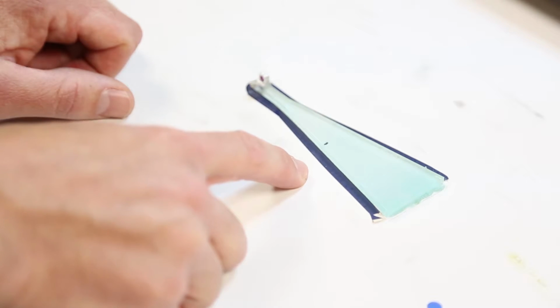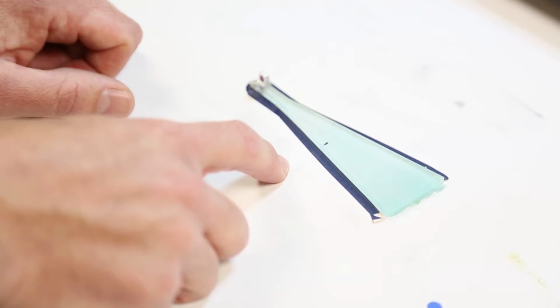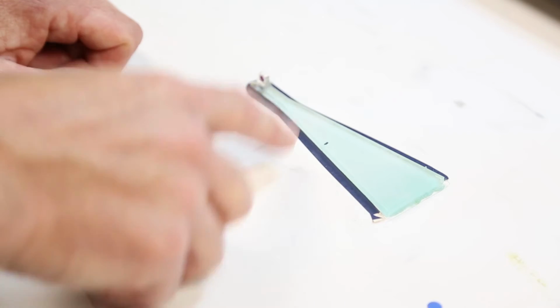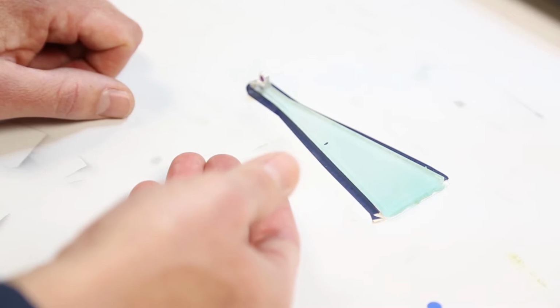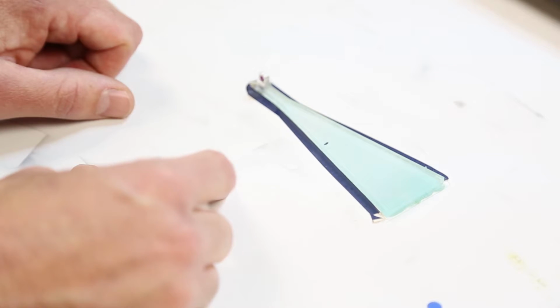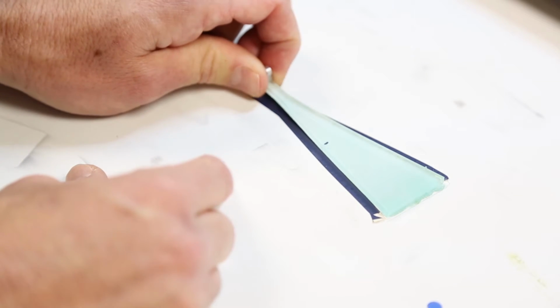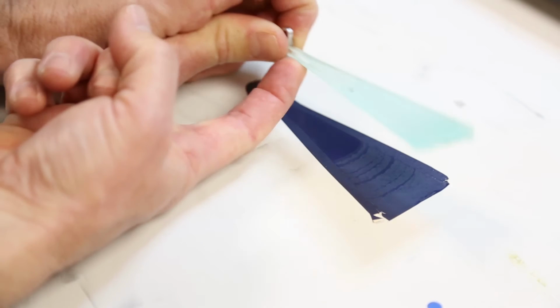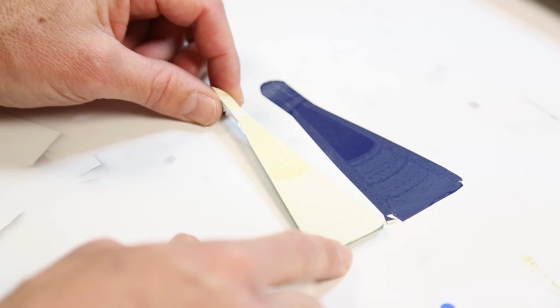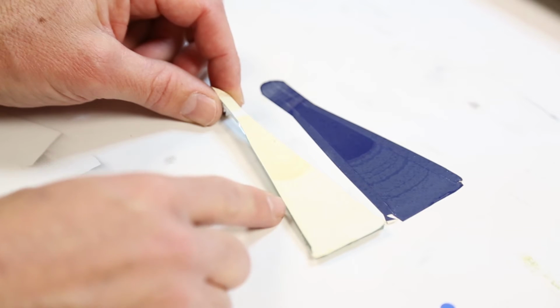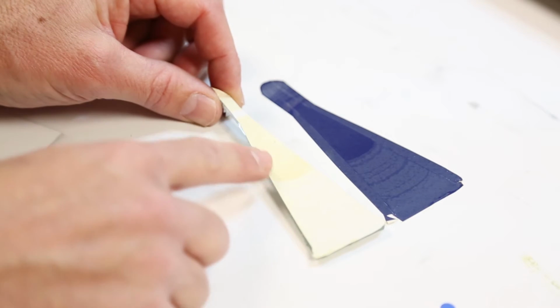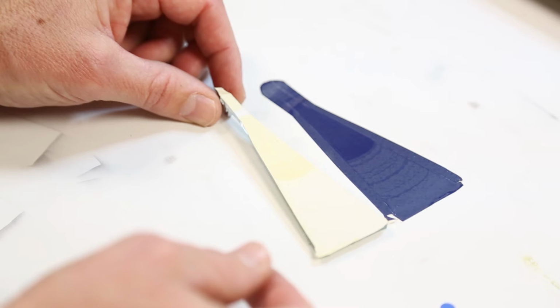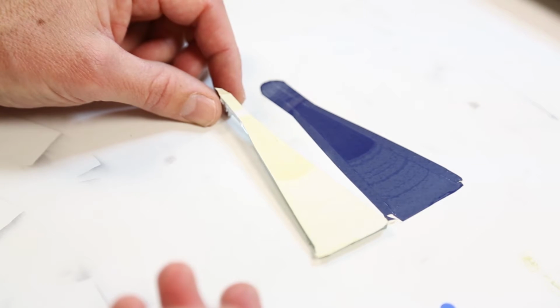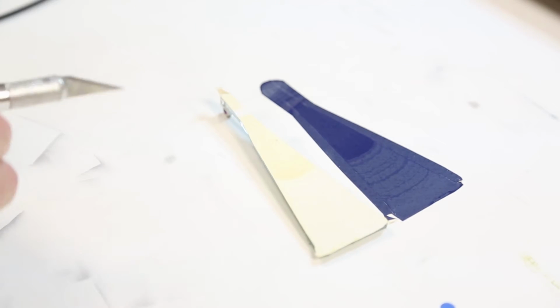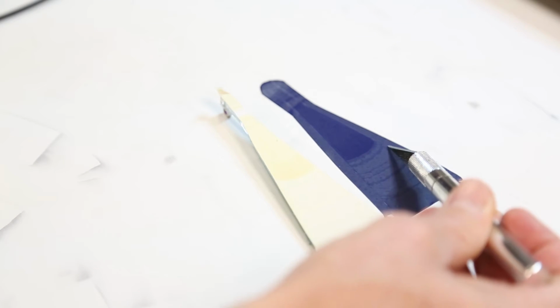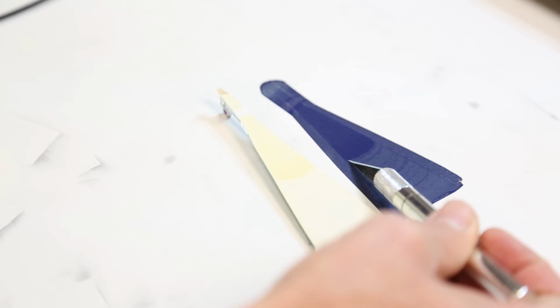Now for the analysis, it's critical that we have an accurate measurement of the debond length. And so I'm always going to advocate looking at the fracture surface to make that accurate measurement. To do that, with most samples, you can simply use your hands and remove it. If you examine the fracture surfaces, you can clearly see the delineation between where the measurement stopped and when you physically pulled the beam off of the module. I think it's most clear here on this blue encapsulant, and it's right about here.